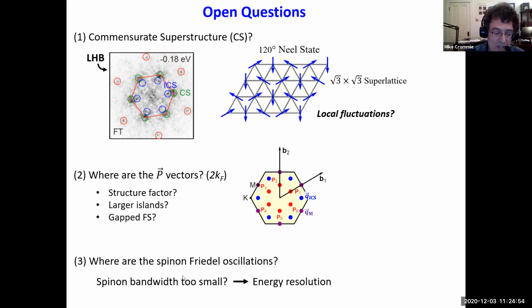And another issue is, where are the spinon Friedel oscillations? We don't see the spinon Friedel oscillations. What we're seeing here are not Friedel oscillations, but by the same type of treatment you would expect to see the spinon Friedel oscillations. One possibility is that the spinon bandwidth is too small and our energy resolution is not good enough, but we're not quite sure. So that's an open question.